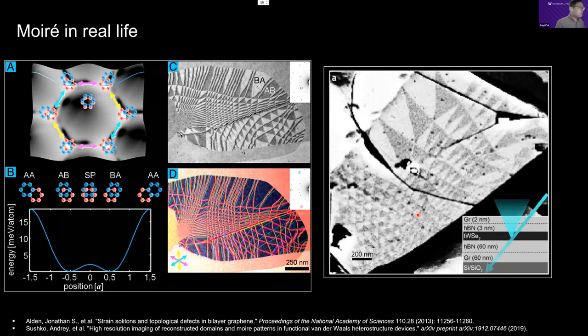But in real life, moiré is something like this. For example, if you naturally exfoliate the bilayer, here is the TEM image, you can actually see that the moiré looks not very nice. If you further artificially stack two more layers together and form a device, the moiré actually has lots of disorder. So if you want to search for exotic quantum phases in this heterostructure, it's actually extremely hard. So then we need to come up with a very smart way to probe those moiré physics at the nanoscale. So, can we probe the moiré physics at the nanoscale?